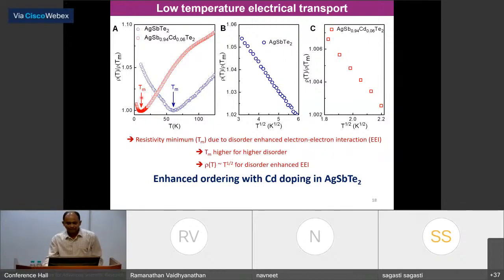And if this minima has a value at high temperature, that means this material is more disordered. For example, this pristine compound AgSbTe2 shows the minima at 60 Kelvin. As soon as I dope cadmium, this minima goes to 10 Kelvin. So this cadmium is actually ordering the silver and antimony, and low temperature data fits that root T dependence that tells that weak localization regime we are working. So actually what we wanted to do, it is happening.